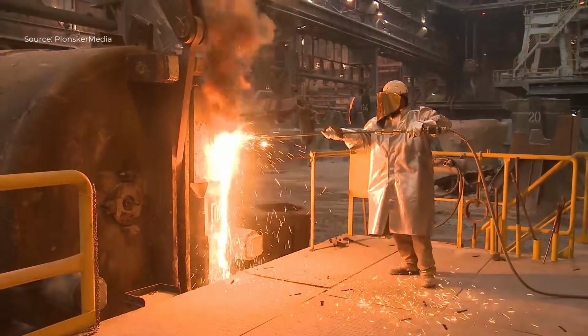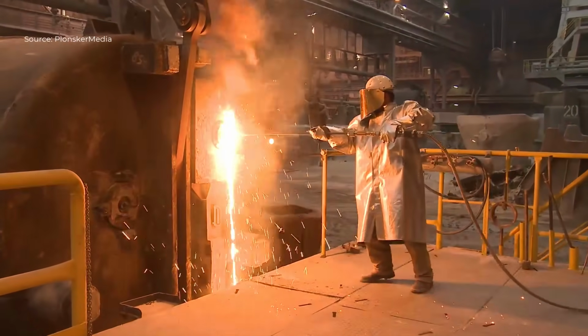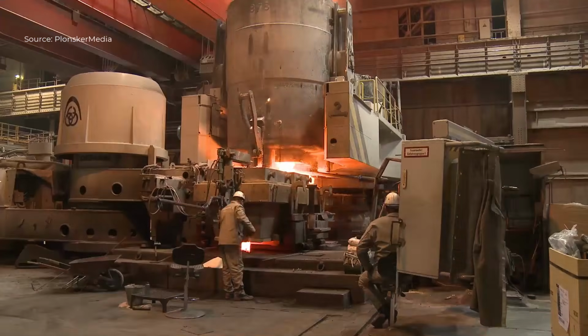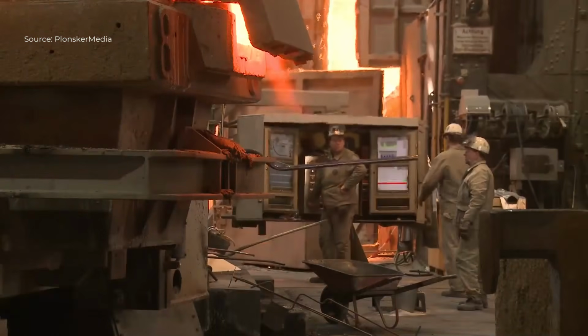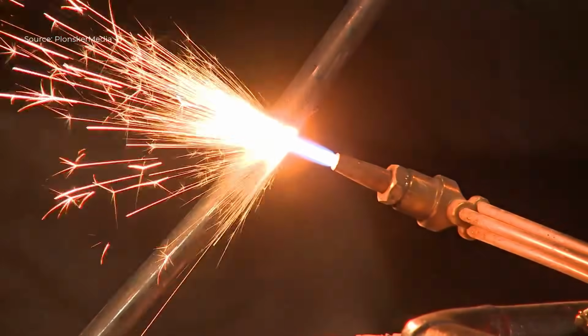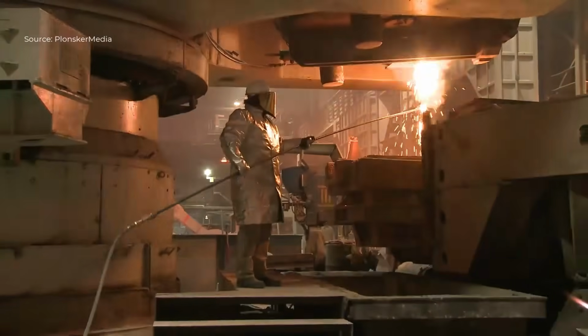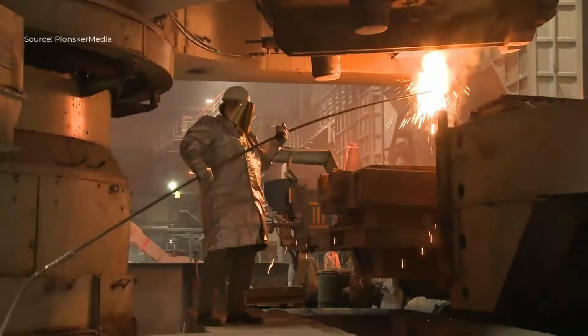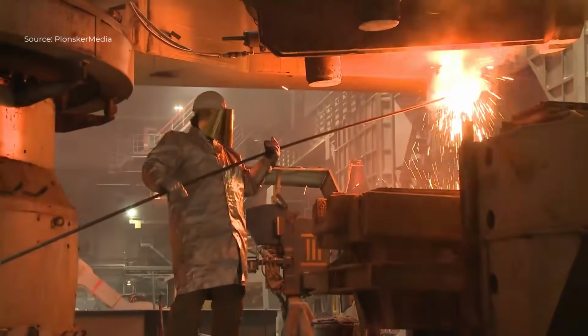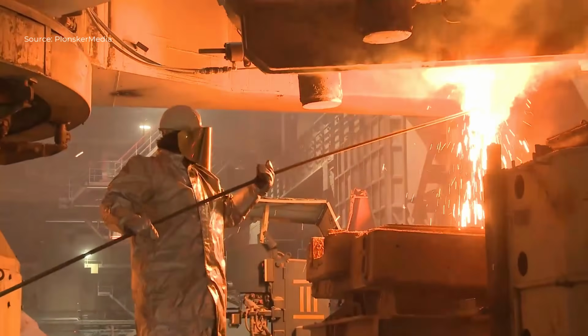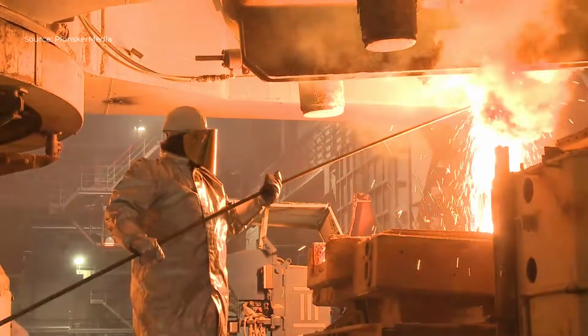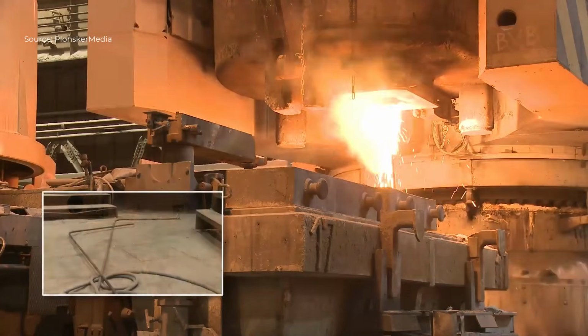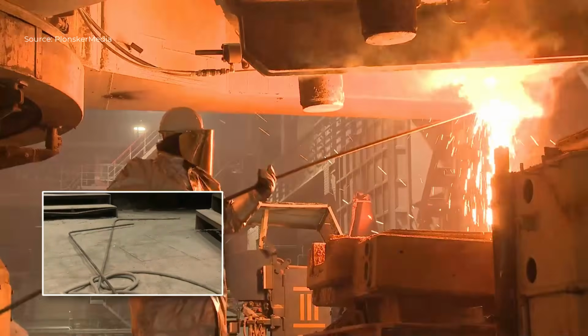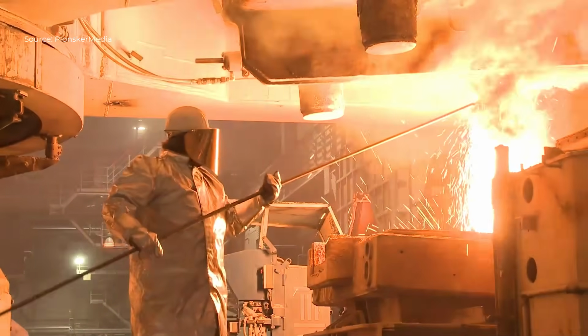During the burning free of the ladle slide gate, there is a risk of backfire, so the oxygen valve must be fully opened only after the breakthrough is achieved. When opening the slide gate at the continuous casting plant, increased danger exists from steel splashes and intense radiant heat. Emergency ladle must be ready.